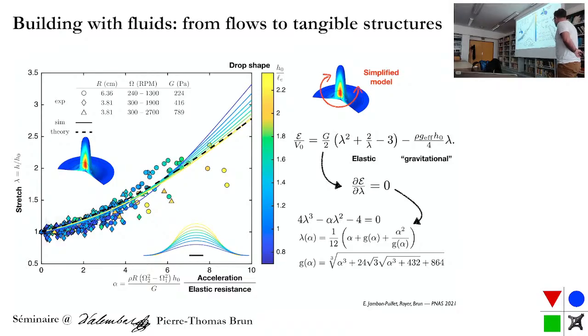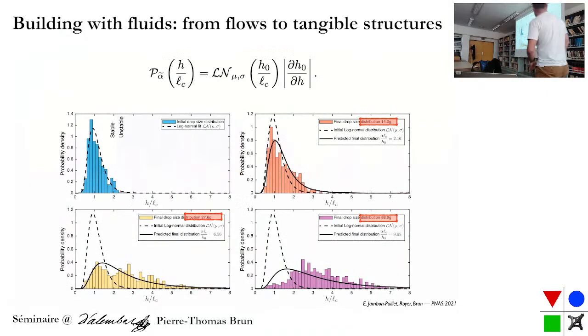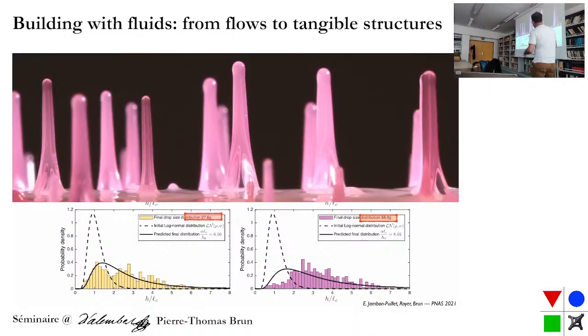And the nice thing about this is that if I have a theoretical expression, I can basically predict what happens to the distribution I had initially. So initially, I have a distribution of droplets, which we fitted with a log normal fit, but it's centered around 1, okay, as we expect. And as we increase the rotation speeds, we stretch this thing, and so we're going to flatten the distribution. And so initially, the model predicts the distribution pretty well. So this is for 14 times gravity. For 27 times gravity, it's not so good. And for 88 times gravity, the prediction and the experiments are quite different. And the reason is because the theory assumes axisymmetry, but actually when you go very fast, you're losing axisymmetry. And so this is a joke I make in every place, but here it's a bit irrelevant. It looks like the Eiffel Tower. Right? So you have this delamination thing, you have these feet that appear.